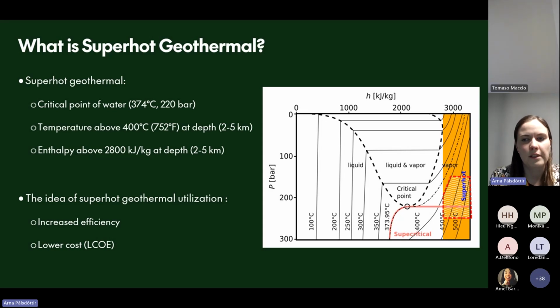We have also, at least internally, been thinking about Superhot as temperatures above 400 degrees C at depths of 2 to 5 kilometers. But really, if we boil it down to what we're actually looking for, we're looking for high enthalpy in the wells, above 2,800 kilojoules per kilogram at a depth of 2 to 5 kilometers. And the idea there is higher enthalpy wells give us increased efficiency in our energy generation, but also more megawatts per well. And that leads, hopefully, to lower costs per megawatt hour, so lowering of the LCOE. Fewer wells and more power is really what we're looking for. And to do that, we need this high enthalpy.